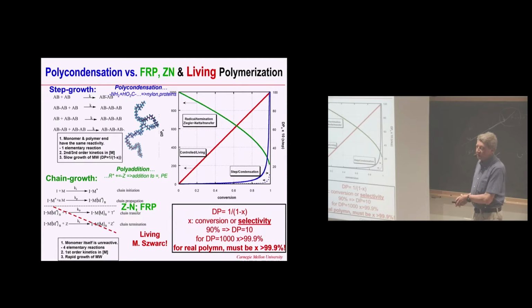And approximately 60 years ago, Michael Szwarc developed so-called living polymerization. He was able to suppress these termination and transfer reactions. And if initiation is fast, in that case, all chains grow concurrently during polymerization, and molecular weight or degree of polymerization increases linearly with conversion. So if you have a ratio of monomer to initiator 100 to 1, at 50% conversion, degree of polymerization would be 50. At 80% conversion, 80. At 100, 100. And then you can add more monomer and continue to grow these chains.